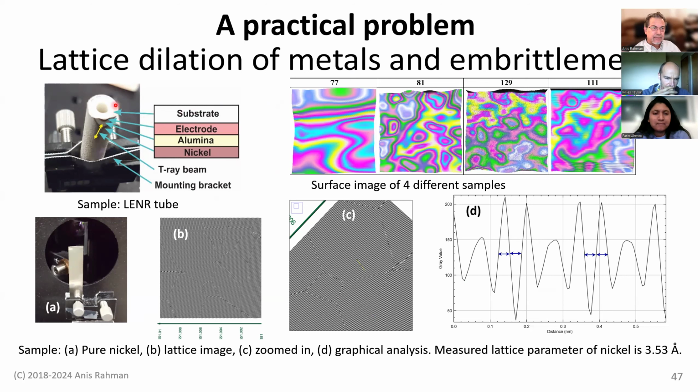So you see this white thing, the substrate, is alumina, Al2O3, right? Okay. And then there is a metallic layer, it's hardly visible from here, but this electrode is copper. And then there's another layer of alumina spray deposited, and then the top layer is nickel. So this is a kind of messy system, if you can think that way.